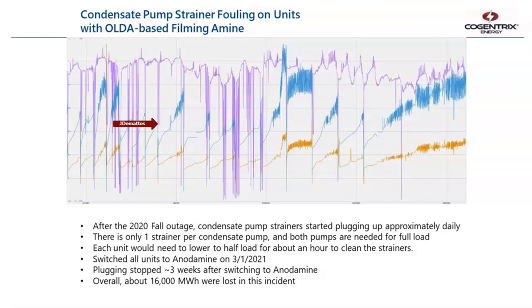We stopped using the amine based filming product as a result of this, and switched the unit to anodamine. I think right about here, in the beginning of March, is where we stopped the amine based filming product, and it took about a couple of weeks, and the condensate pump strainer plugging issues went away. So that's why I attribute it to the amine based filming product. It's possible that there could have been multiple causes, but